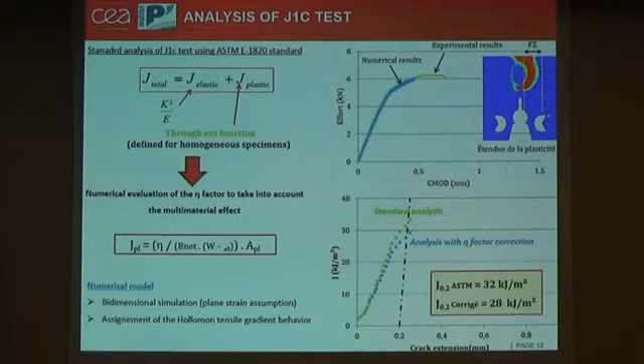For quantitative evaluation or characterization of the welded joints, we propose to use the J integral. Normally, for such analysis, we are based on the ASTM standards, but it will not be easy to use the ASTM as we have a multi-material effect by the presence of the fusion zone. Here, as we can observe on the plasticity development, we have a dissymmetry of plasticity that will induce a dissymmetry of loading, and this will have a non-negligible impact on the eta factor linking the plastic area to the plastic component of the J integral. Finally, on the J values, we have a difference of 4 kJ per square meter between standard analysis and an analysis based on numerical results, which is not negligible for this material.